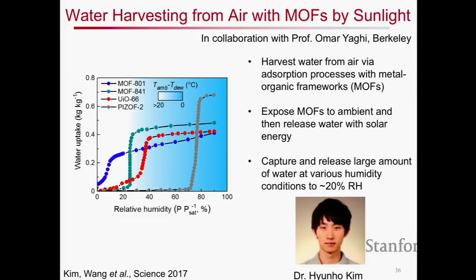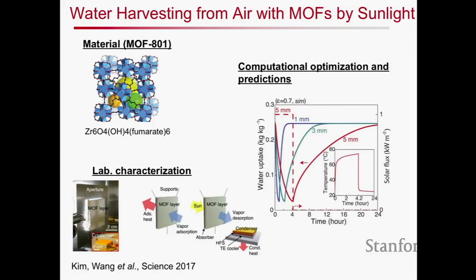So we were focused on these metal organic frameworks with this sharp step because not only does this allow us to capture the water vapor at these low humidity ranges, it also allows easy release because of the steepness of the isotherm. Incorporating these metal organic frameworks has been a process by which we've been able to not only characterize the material itself, but also optimize its characteristics and consider the heat and mass transport processes in this material set, and characterize them at the lab level in a layer type structure before we were able to develop a device.